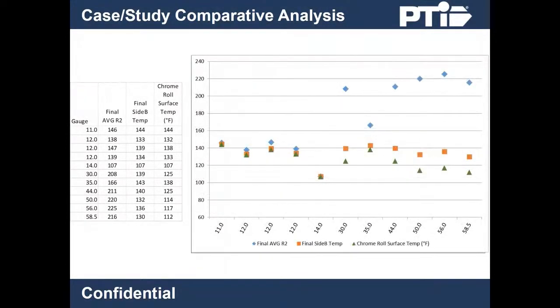Here's another look at the same data sorted by gauge. Notice how the data points converge for the thinner gauges and greatly diverge for the thicker gauges. Another note, look at the massive divergence of the 30 mil as compared to the 14 mil and the 35 mil right next to each other. This data suggests that this process was pushing the limits of the roll stand. This emphasizes the importance of accurate, detailed thermal modeling.